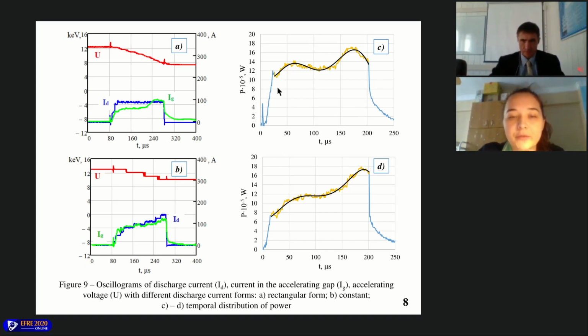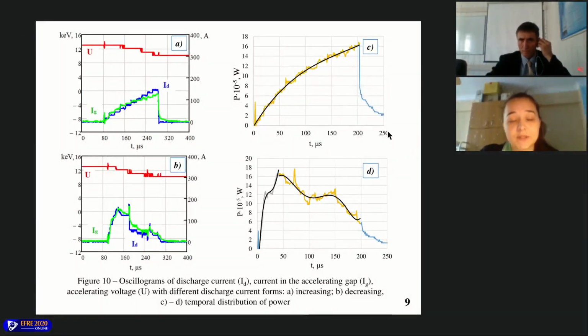You may see that the form of the power almost repeats the form of the current in the accelerating gap. The same situation is in figure 9, B and D. Also, on slide 9, you may see two different ways of putting in the energy. 10C shows the increasing trend, and 10D shows the decreasing trend of putting in this energy. So by controlling the amount of power, we also can control the temperature of the surface and the way it changes.